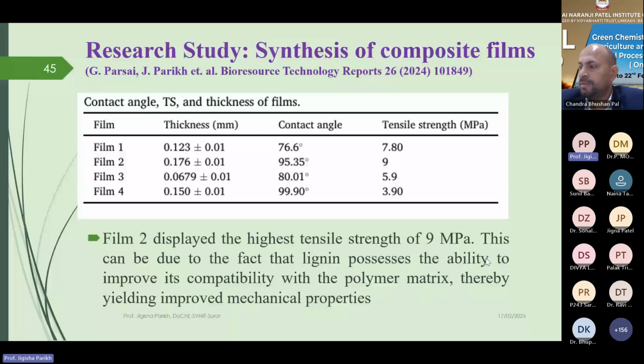of the films. Okay, so these are a few features of the film with reference to the component. So thickness ranging from 0.068 up to 0.176. Contact angle is received. This contact angle is with reference to identifying whether it is hydrophilic or hydrophobic. Okay, so if it is hydrophobic, then we can utilize this for food packaging where moisture is not required. Okay, similarly, tensile strength has also been measured, because durability of the film is very, very important.